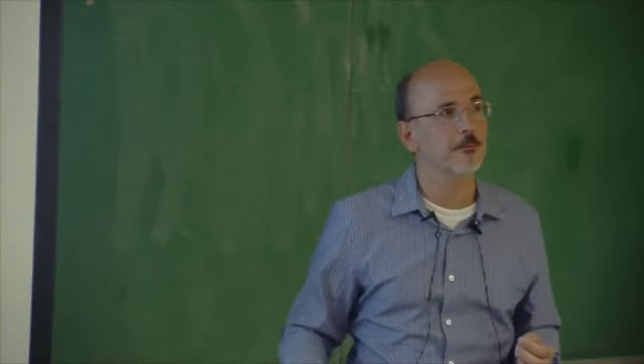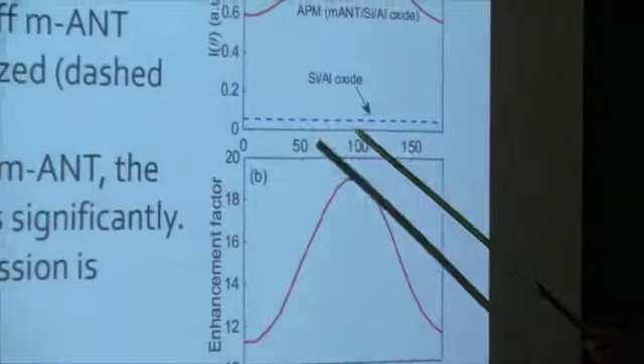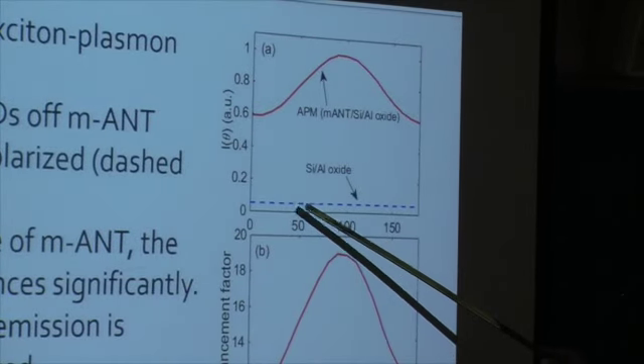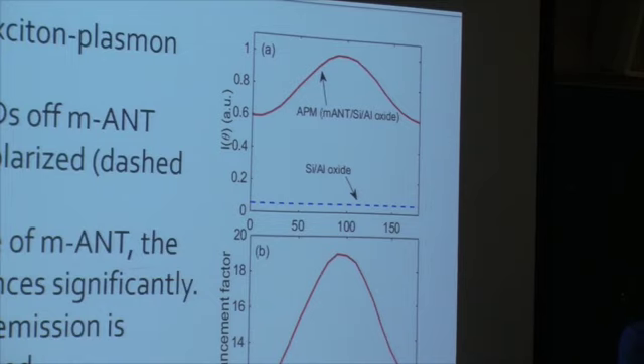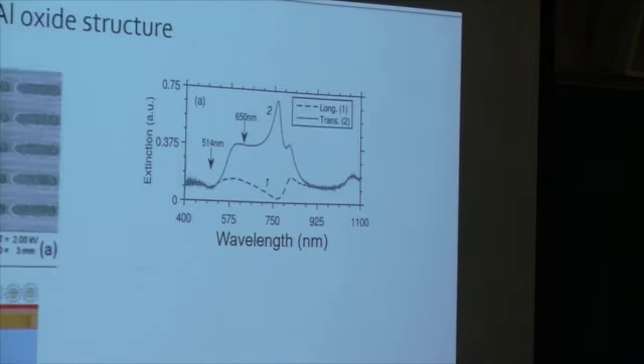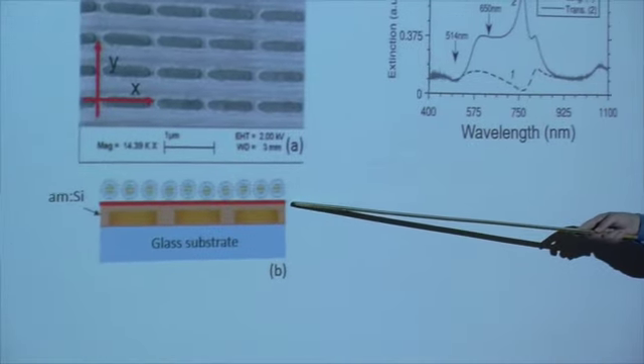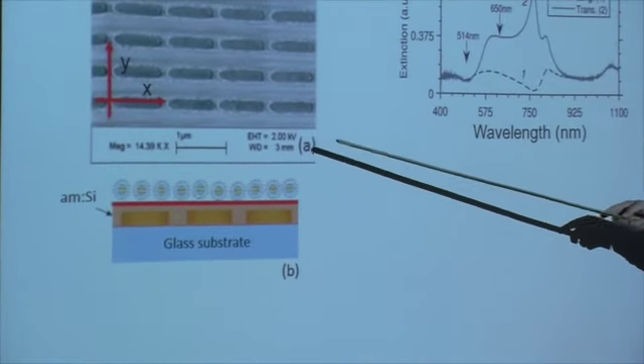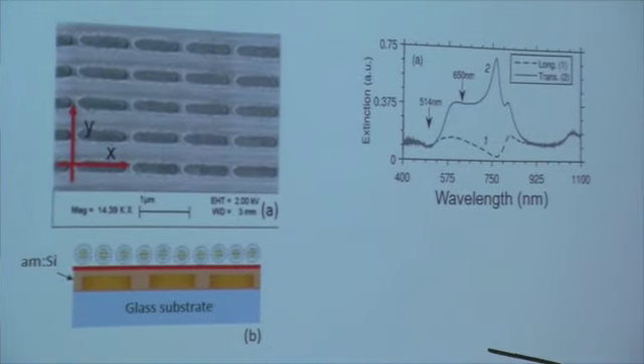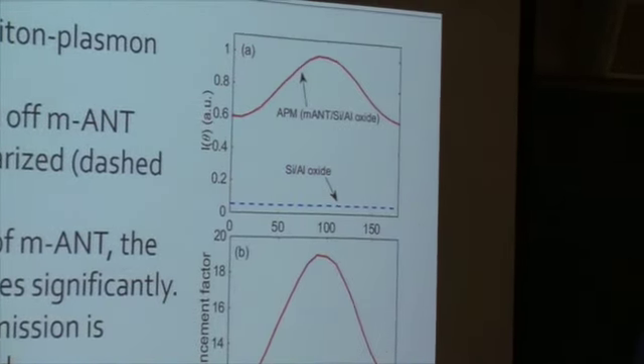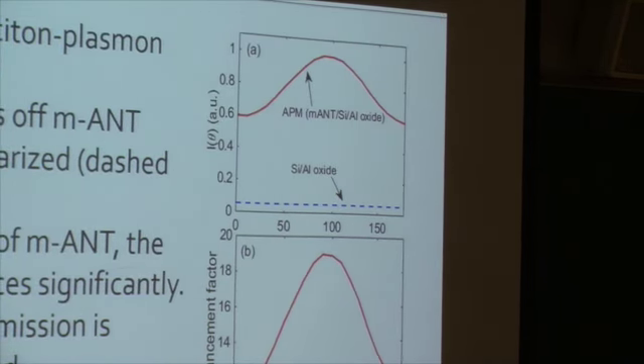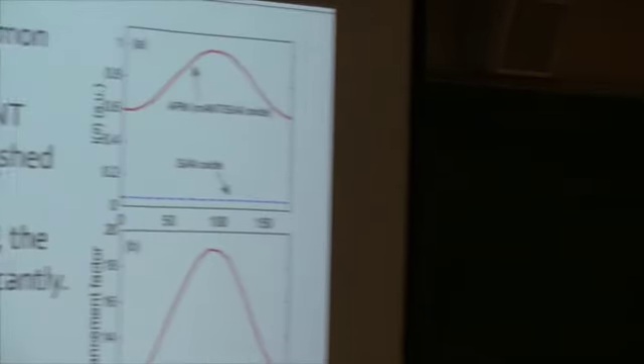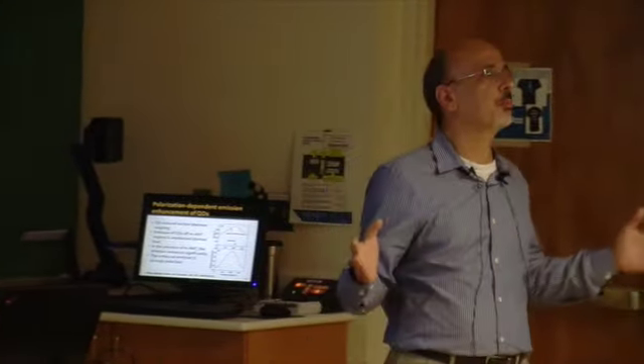But now, let's look at the emission that is coming out from the quantum dot. If you look at this slide, the dashed line is the emission of the quantum dot coming from a similar structure as here, but there is no metallic nanoparticle underneath. So it is coming from quantum dot on silicon underneath glass. And before light goes to the spectrometer, we put an analyzer, so we know the polarization of it also. We analyze the polarization. And you can see that the light that is coming out from the quantum dot is not polarized.